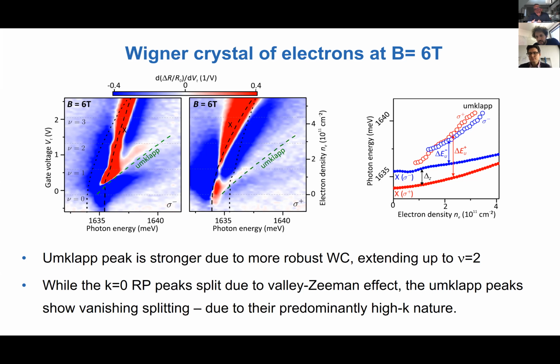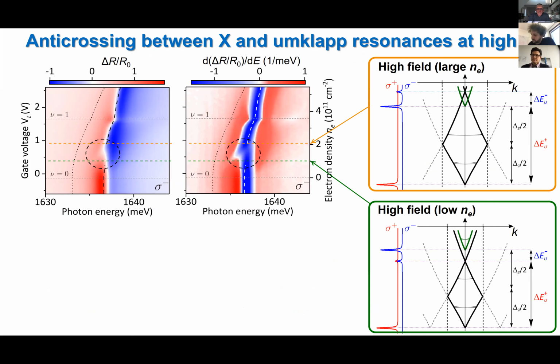Well, as we increase the electron density, in our system at least, we seem to lose the umklapp peak. Even though we increase the interactions at higher densities, the r_s parameter is becoming smaller, right? So the kinetic energy is becoming more important. And so it is actually expected that at higher densities, the Wigner crystal would destabilize. And again, as I said, we tentatively argue that this is what happens here.